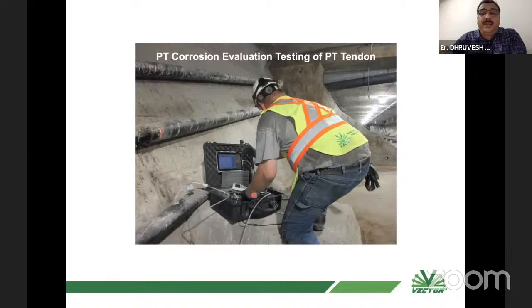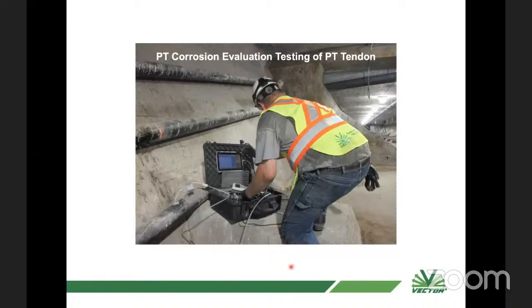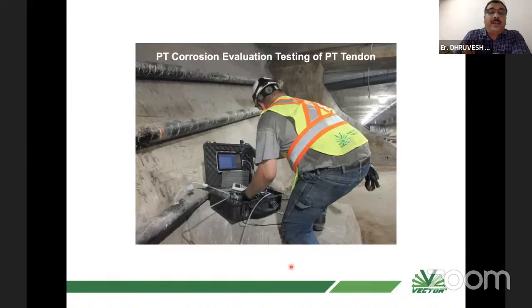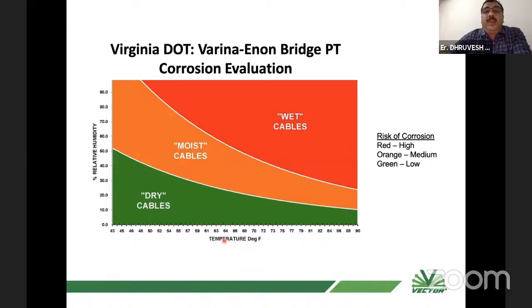This is a view of a bridge in Virginia, where I was part of checking the evaluation and the PT implementation also. Here, this is the port, this is the point where the drill was done, and then a small pipe was put and connected to know the moisture content, and dry gas was injected from the other side, and we are measuring the flow and the moisture content. And at that particular bridge, we found that at most of the locations there is very high moisture content. And when we broke open, we found that the tendons were really corroding.